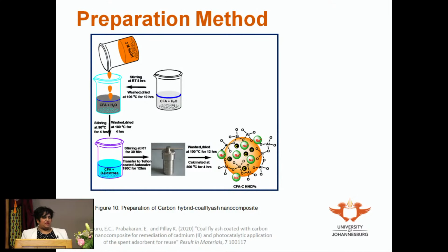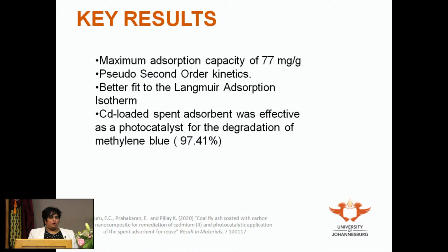So the picture in the slide highlights how we prepared this carbon hybrid nanocomposite, which was coated onto coal fly ash via a hydrothermal technique. And then we observed a reasonable adsorption capacity for cadmium-2 removal, but the highlight of the study was really that it did work as a photocatalyst. We observed 97.41% degradation of methylene blue dye when we attempted reusing the cadmium-loaded spent adsorbent.